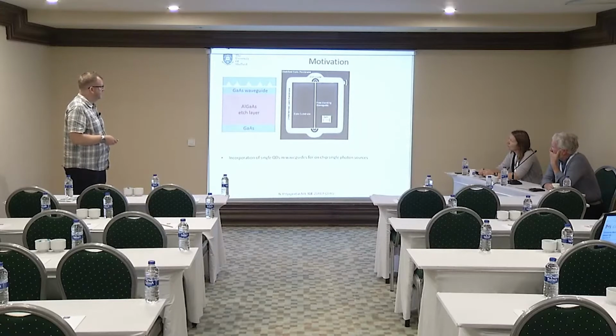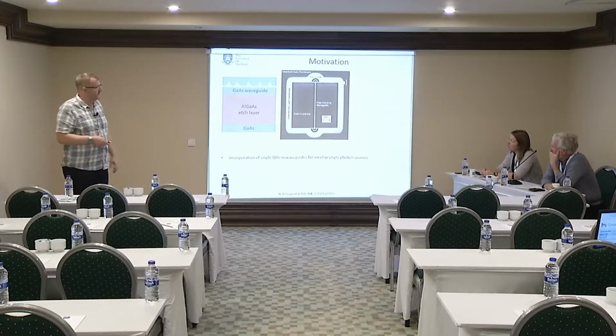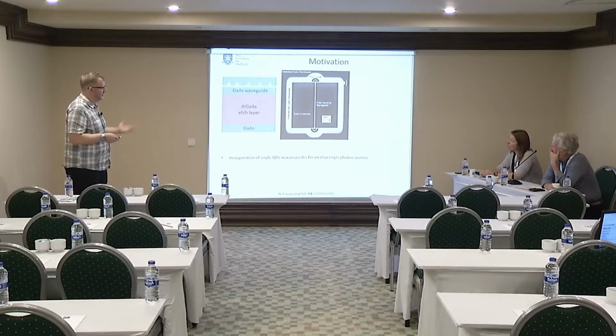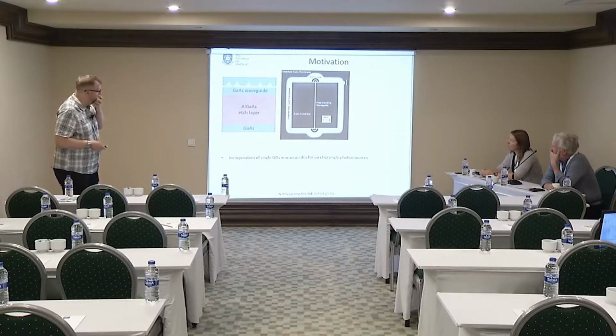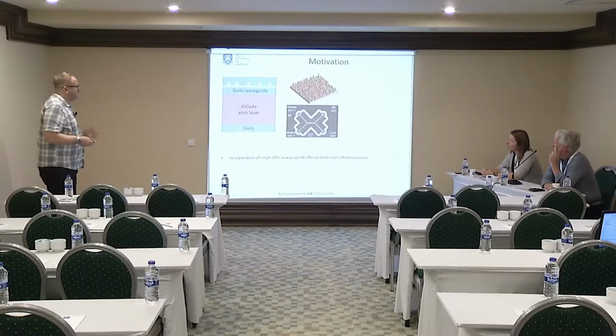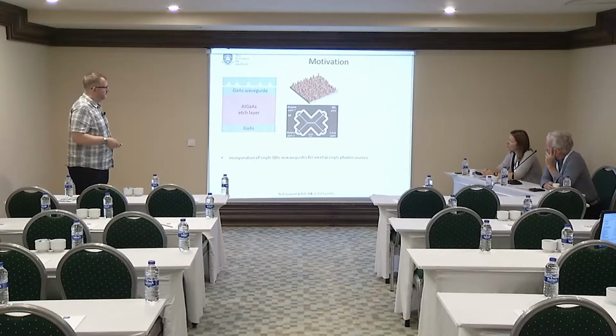We have a sacrificial layer of material that we etch away to leave a suspended membrane with the dot layer. This is perhaps not the most exciting waveguide, but if you have a dot somewhere here and you shine a laser on it, then the light transmits along the waveguide and we scatter it out through these couplers. We could go to a slightly more complicated device. Now we have a beam splitter.